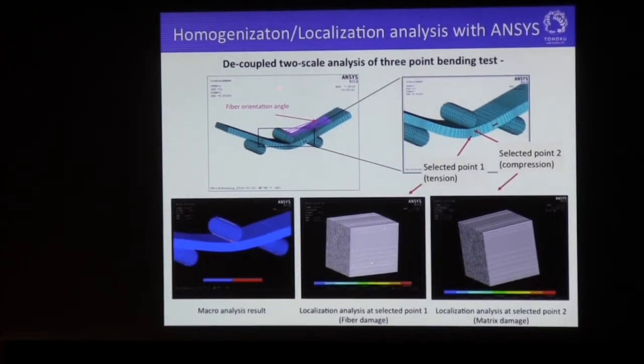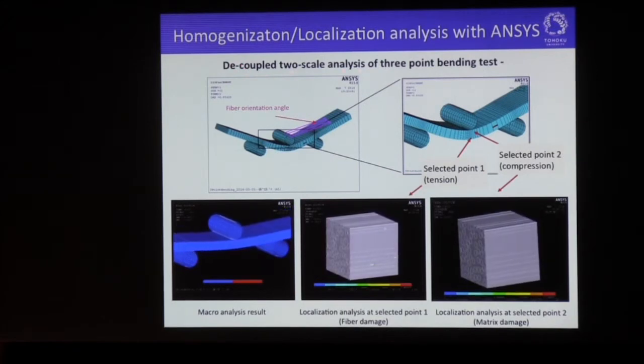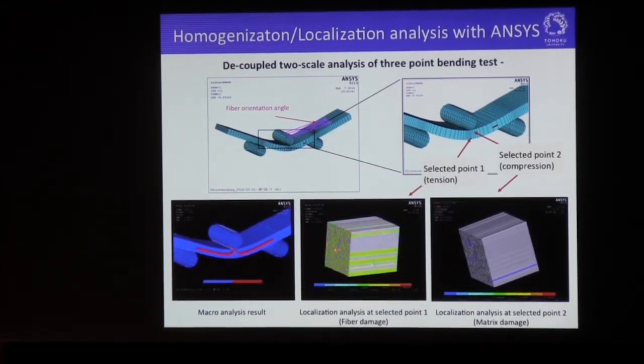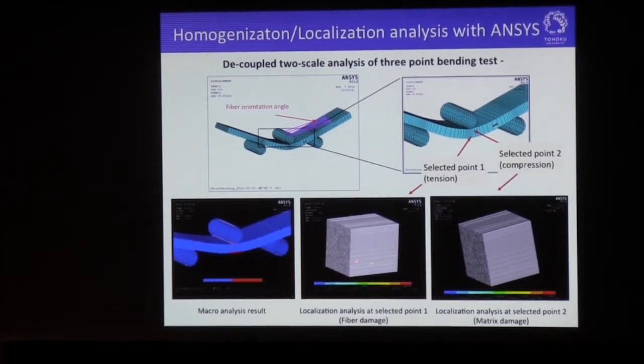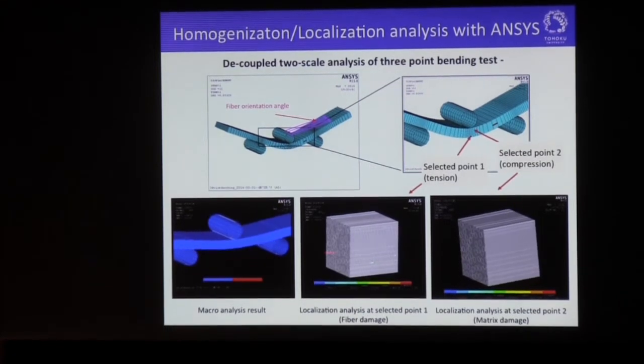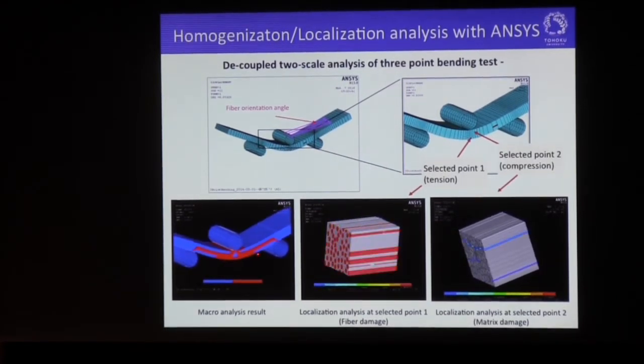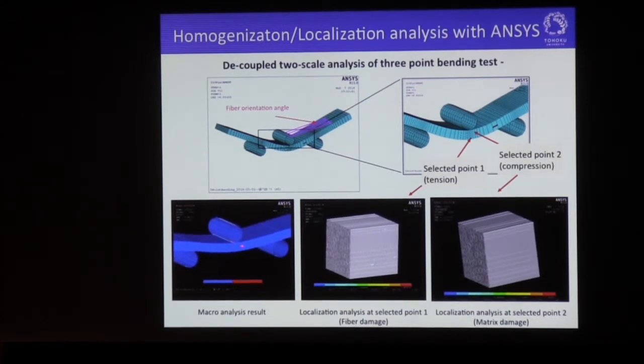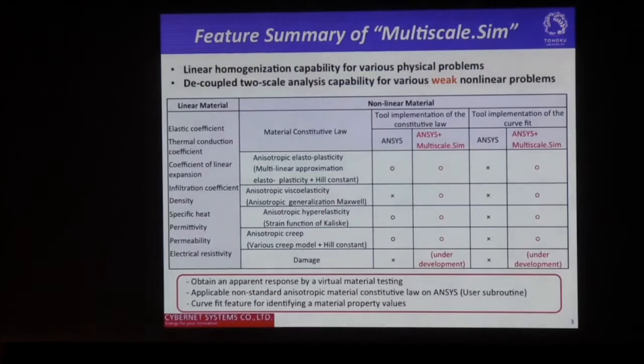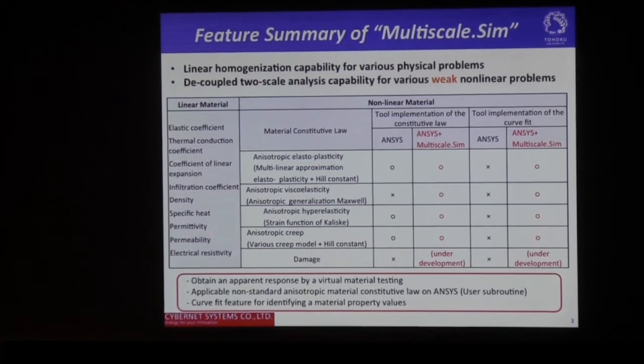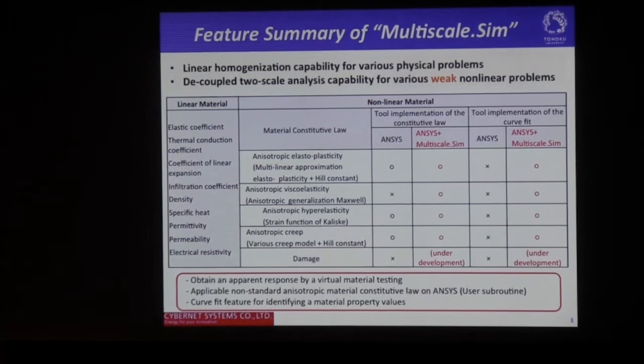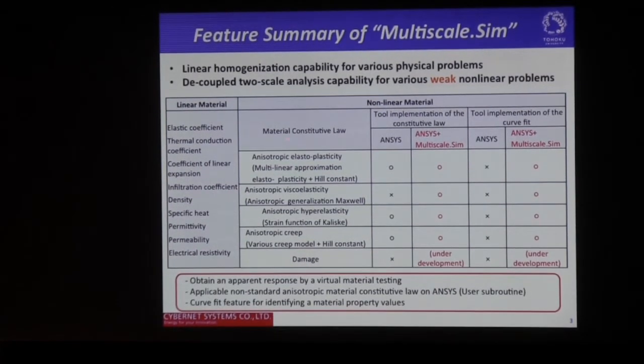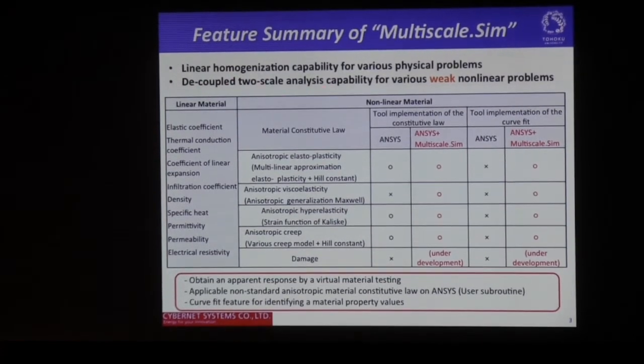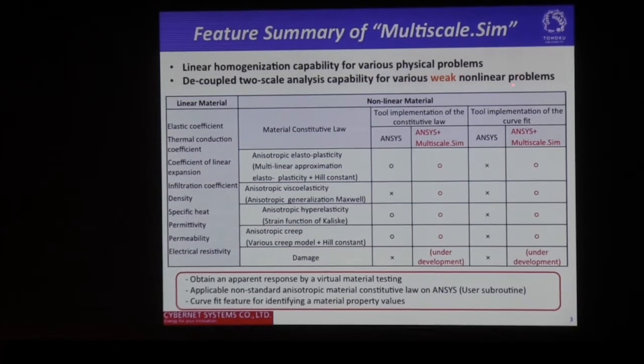So let me show you a very simple numerical example using this software, that is decoupled two-scale analysis of a three-point bending test. As you can see, this is the localization analysis result during this macroscopic deformation. As you can see, the fibers are damaged in the tensile region of this macrostructure, and also the matrix is damaged in the compressive region of the macrostructure. Okay, this table summarizes the features of the Multiscale Sim. This product provides linear homogenization capability for various physical problems. You can see here. And also look at this table. This product provides decoupled two-scale analysis capability for various weak nonlinear problems.